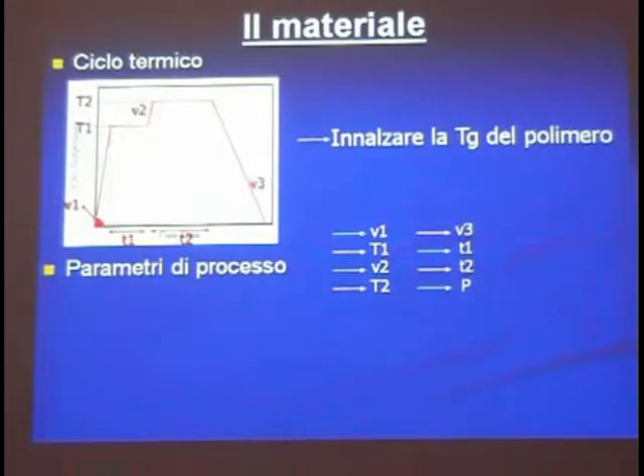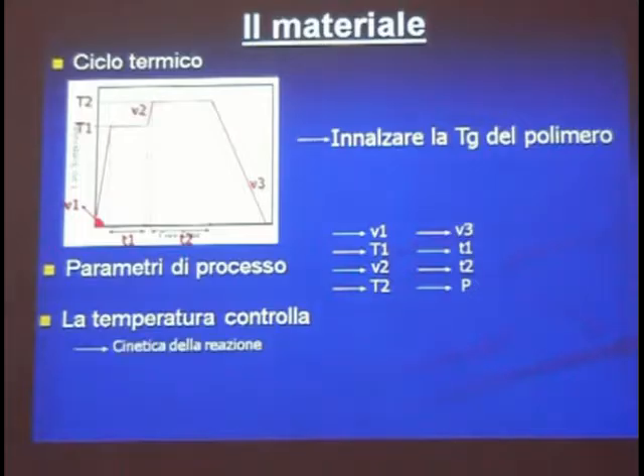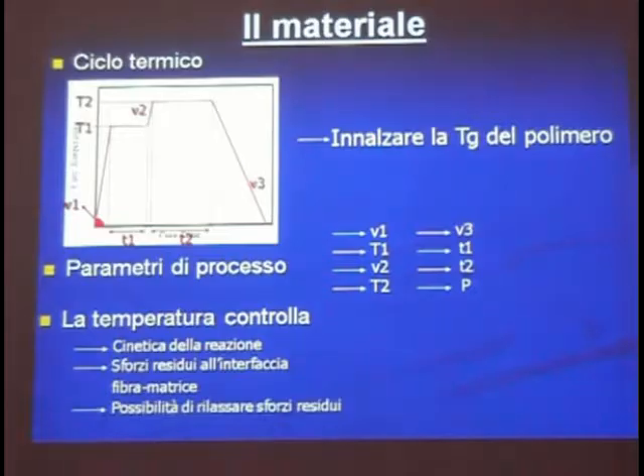The processing parameters are many: the heating speed, the temperature at the two steps, the cooling rate, and the times T1 and T2 of each step. Basically, the temperature controls the kinetics of the reaction, and then sets the level of the residual stresses that arise at the interface between fiber and matrix, and their possibility to relax during the cooling time, and that's the reason why the cooling time is kept as long as possible.